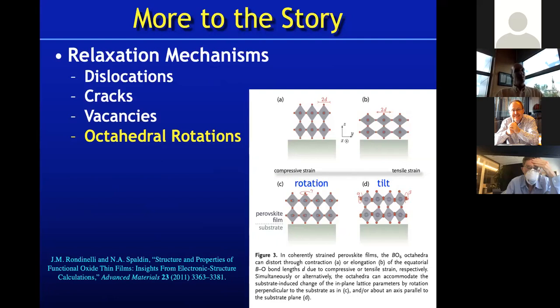Now, perovskites themselves deviate from having a tolerance factor of 1, and as they have tolerance factors that deviate from 1, in fact, most perovskites do not have the cubic perovskite structure, and the way that they accommodate that tolerance factor is to bring in rotations and tilts. So it's well known in perovskites. In fact, most of the substrates that I showed you have rotations and tilts in them.